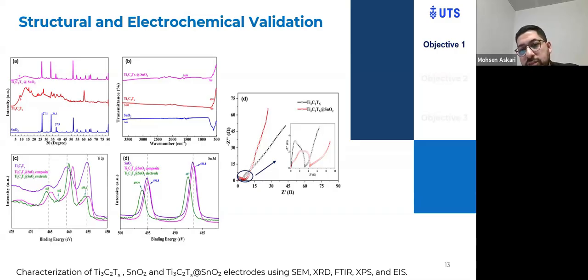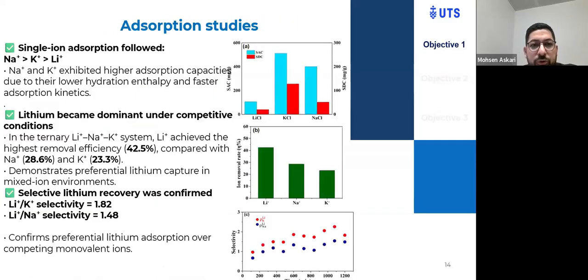The EIS shows that using the SnO2, the conductivity will increase, and lithium ion accessibility and the pathway for lithium ion transport will be improved. We ran the CDI test for the adsorption study in single ion adsorption of sodium, potassium, and lithium, and the ternary of these ions.